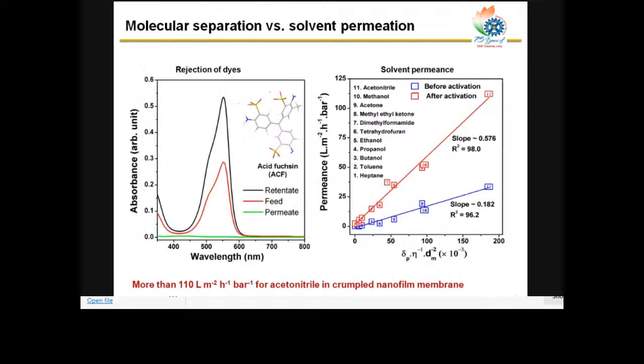So for molecular separation, what we have done, we use a very similar technique to what I discussed in the previous example. We took a dye molecule here, acid fuchsin. We applied pressure with a feed containing acid fuchsin molecules, and we collected the permeate. Here we see the permeate has no acid fuchsin molecule coming through the membrane. That means the membrane has a pore size which is smaller than the size of the acid fuchsin.